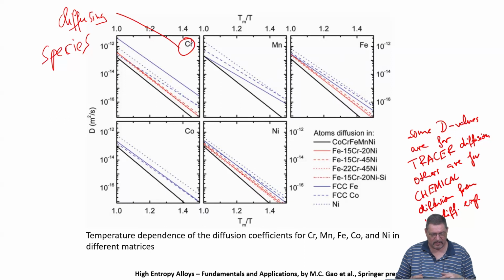But it's very inaccurate to use this graph for this comparison, because you compare different diffusion coefficients, which are not the same, which must be different because of their physical definition. And also, if you look at it, the difference is not large, right? And we compare here single elements as a matrix and maybe ternaries, and then we go to 5-component, which means you would expect some change in any diffusion coefficient to happen if you change the alloy system, when you have more disordered lattice occupation and so on.